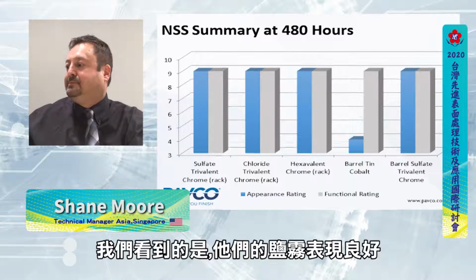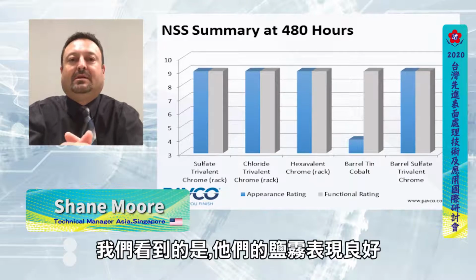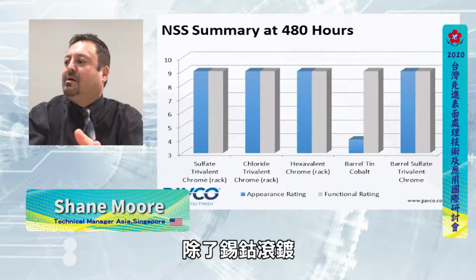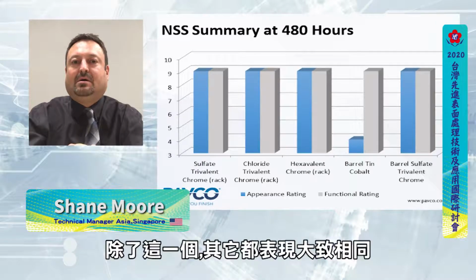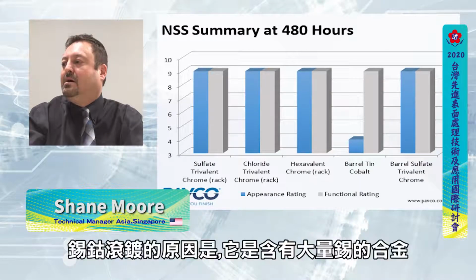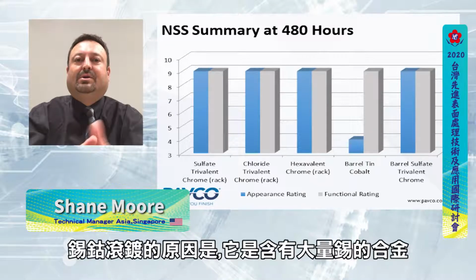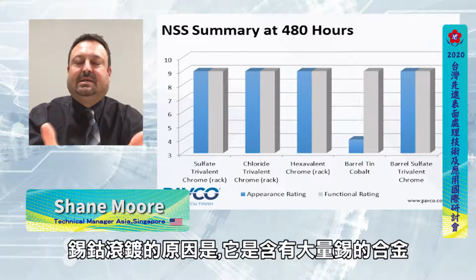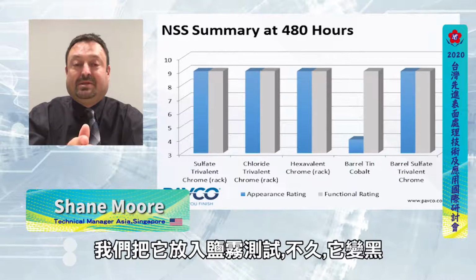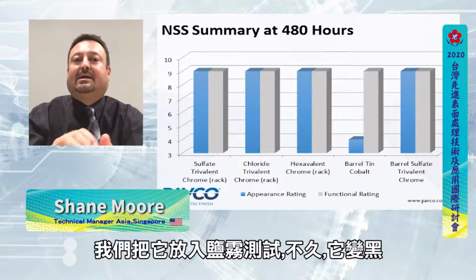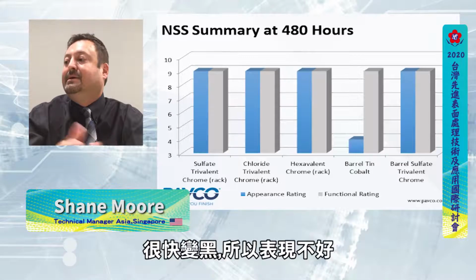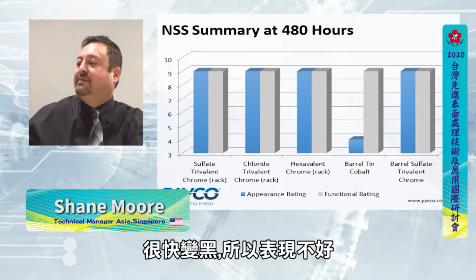So what we saw was that they all performed pretty well in the salt spray chamber, all except for the barrel tin cobalt. Other than that, they all performed roughly about the same. And the reason for the barrel tin cobalt, it has the tin-rich deposit, the tin-rich alloy. It was pretty soon after we added this to the cabinet that it went dark almost immediately. So that didn't get a very good rating.